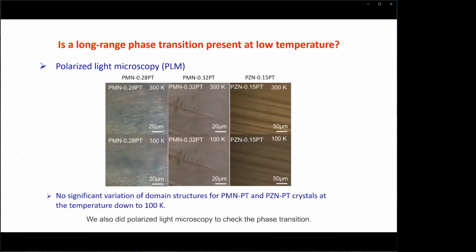We also did polarized light microscopy to check the phase transition. It shows the same results as the XRD experiments, as shown here. The domain structures of these three crystals do not change from room temperature down to 100 Kelvin.